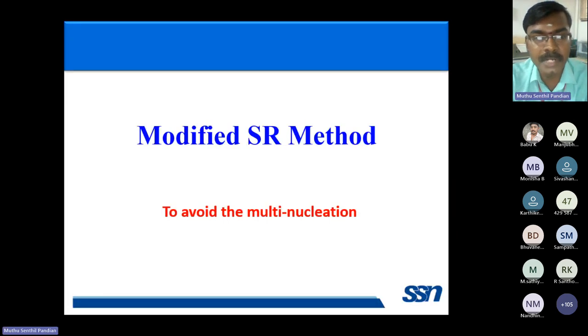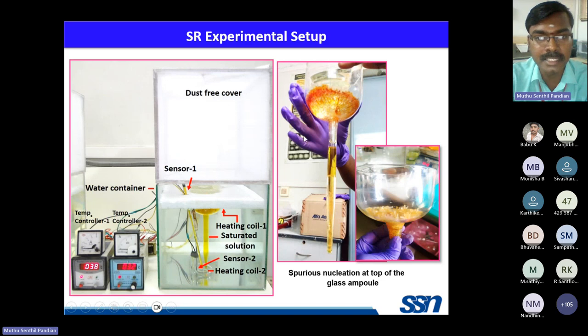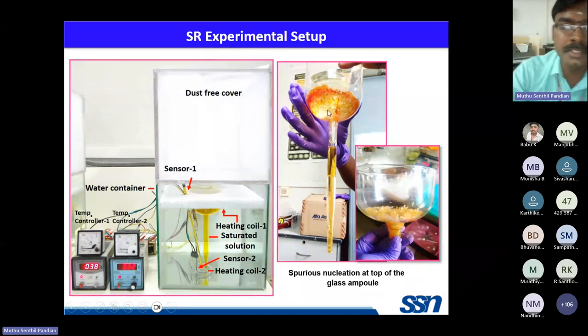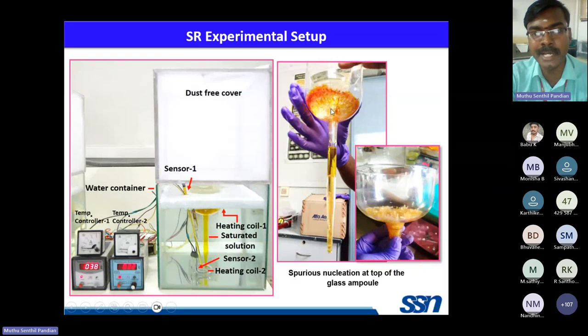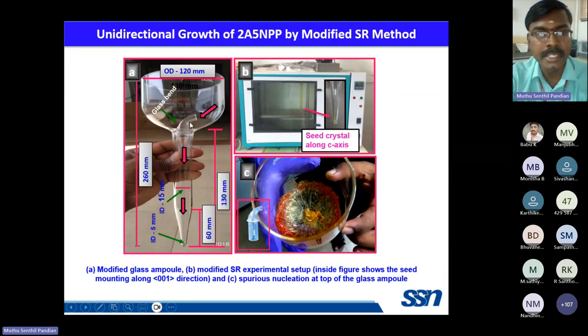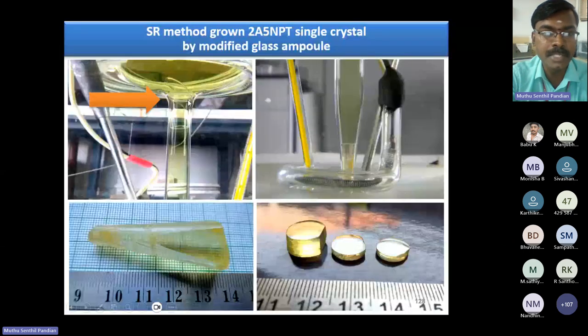And we have made several modifications in order to avoid the multinucleation and impurity segregation in the SR method glass ampoule. When we use solvents like acetone, ethanol, or methanol, the multinucleation will form at the top of the SR glass ampoule. In order to avoid the multinucleation formation at the top of this glass ampoule, we have introduced this glass pin. Using this glass pin, one can easily minimize or avoid the spurious multinucleation formation at the top of the glass ampoule.